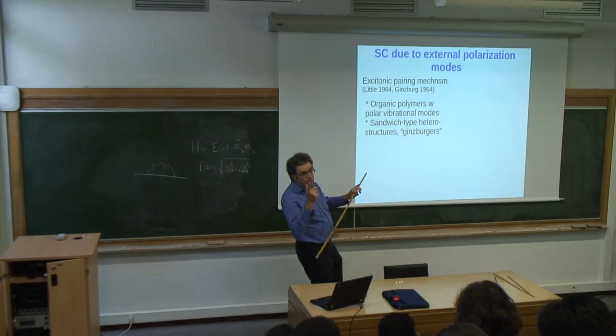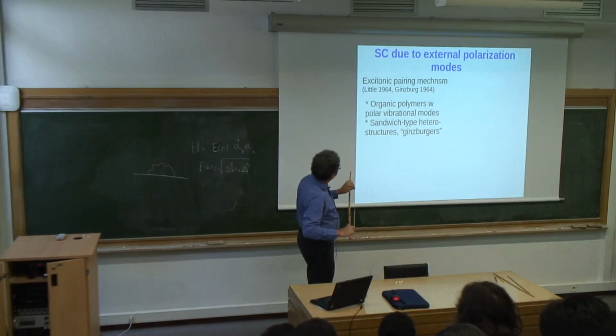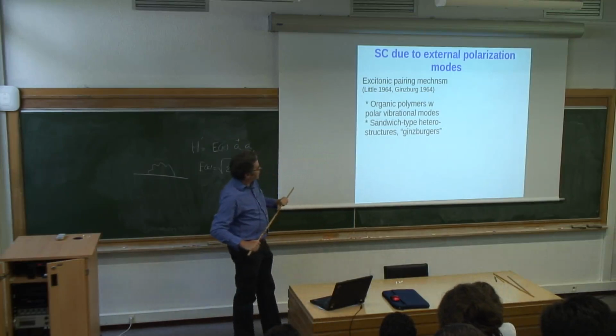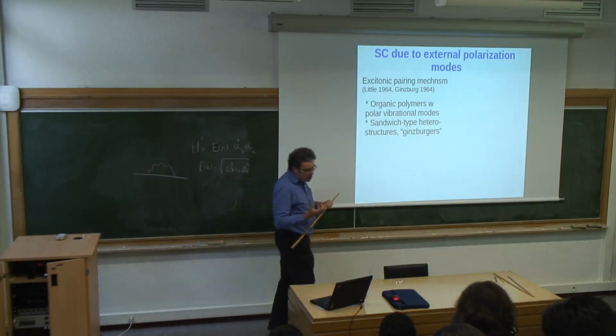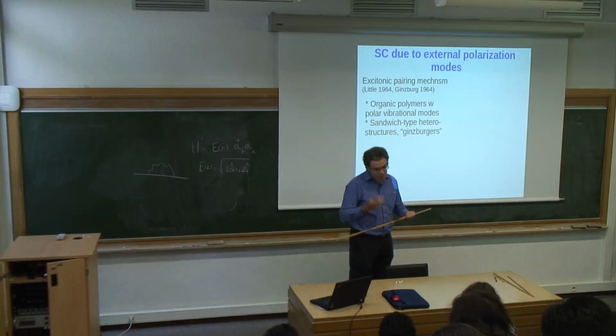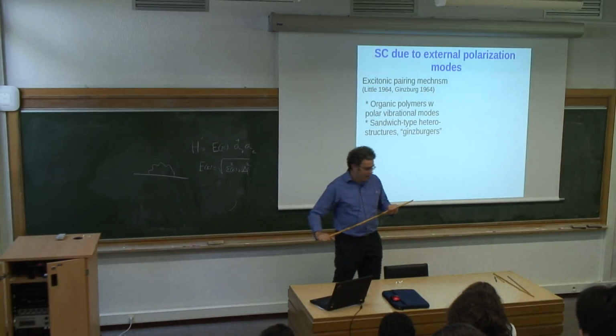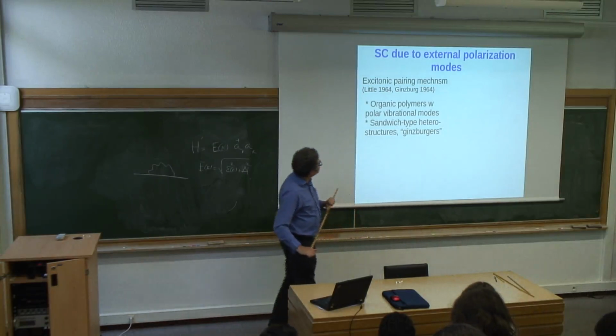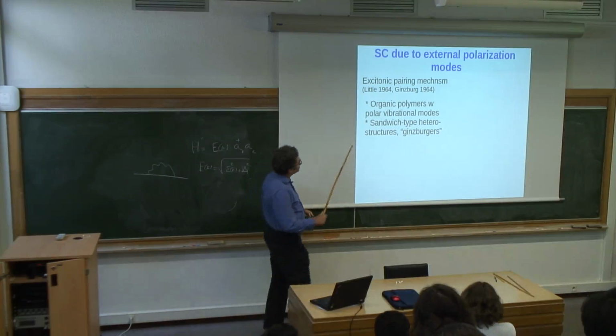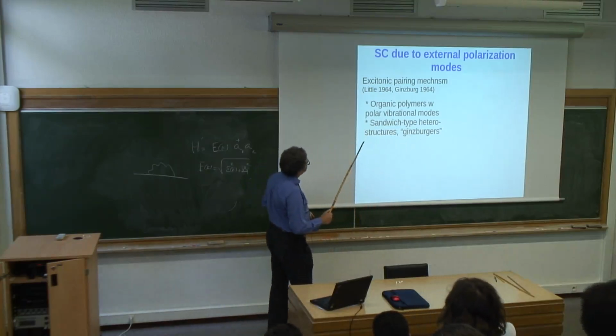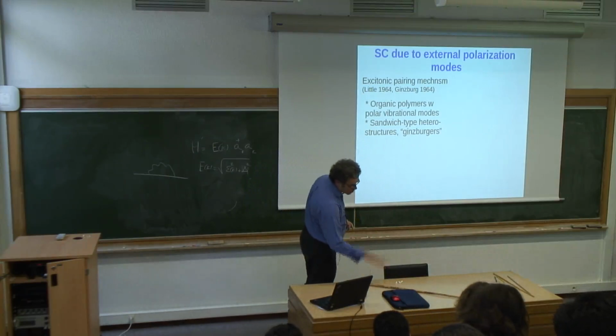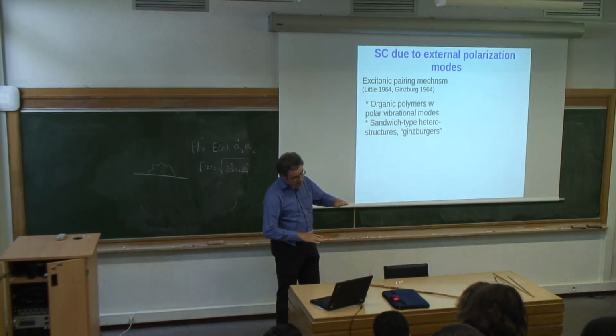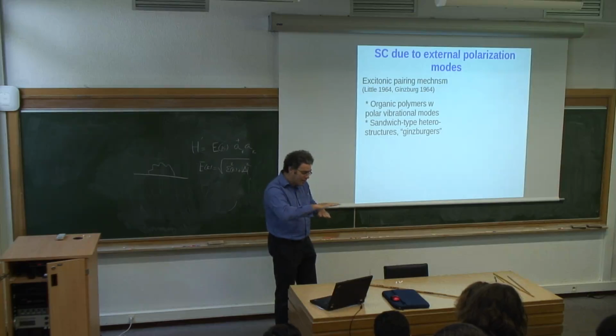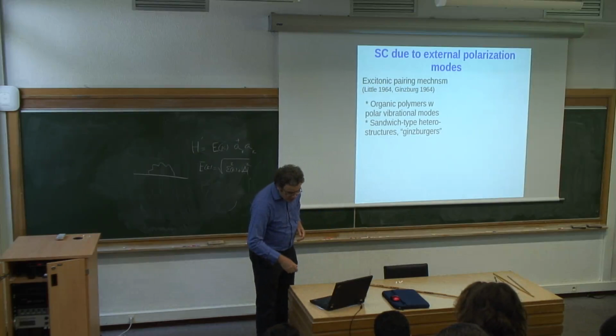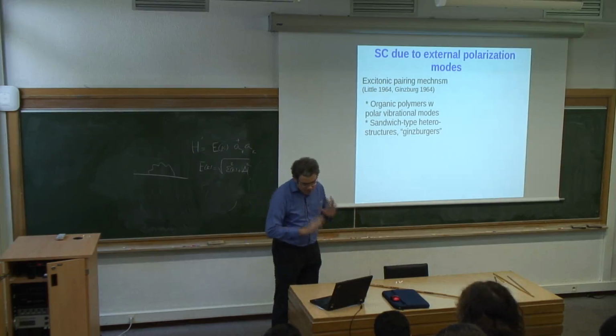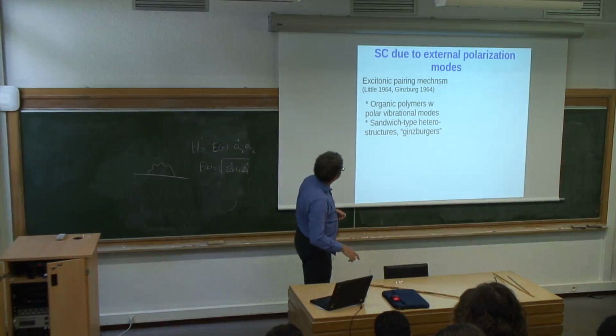and said that because of this attraction that you just mentioned, we'll get a pairing interaction, and because in organic molecules the main constituent is carbon, and carbon is very light, and the phonon frequencies can be very high, you can get a very sizable attraction. And similar ideas were proposed by Ginzburg, who was thinking about layered structures of having a superconducting film, and then some dielectric with polar phonons on top, and that started an avenue of research that continued for some time.